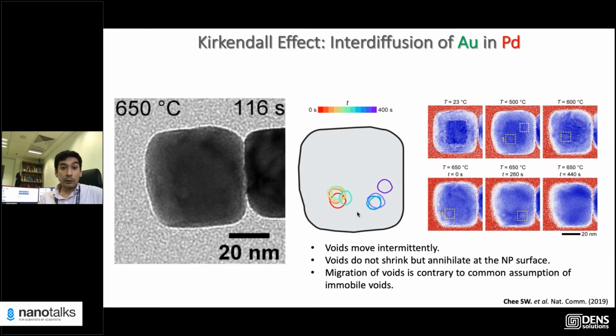But these voids also eventually move to the surface, and then they just disappear. One key point to note is that in the classical Kirkendall description, you expect them to be stuck and grow in size as you heat. But this is not what we see. These are very flexible.